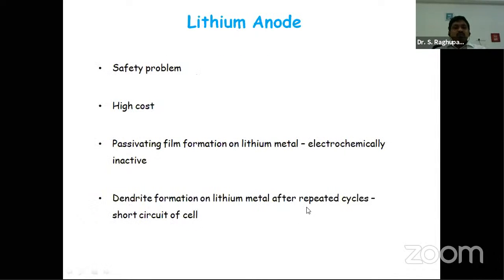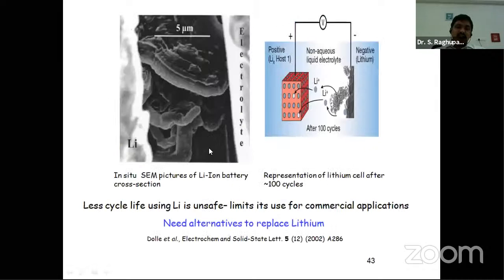With the lithium anode, we are facing a few problems. At the beginning, lithium was explored as an anode, but lithium has safety problems and the cost of lithium metal is very high. A passivating film is formed and there is dendrite formation, which you can see in the next slide. After a few cycles, you can see in some images there is dendrite formation. Lithium metal comes out of the foil. Whatever lithium foil you use, it just comes out.